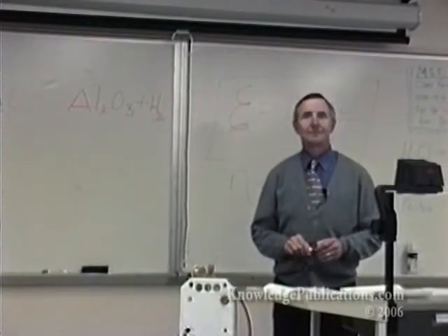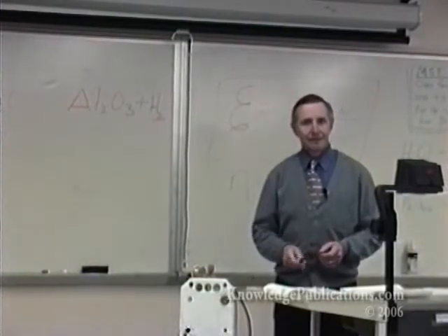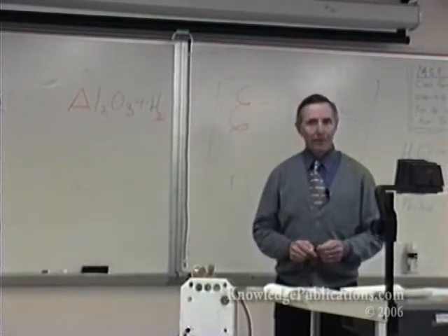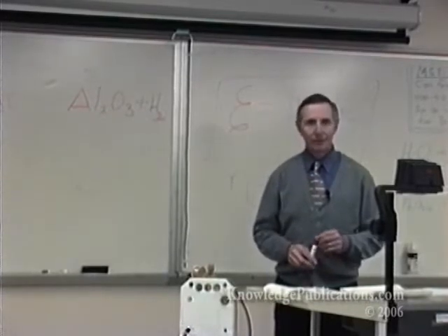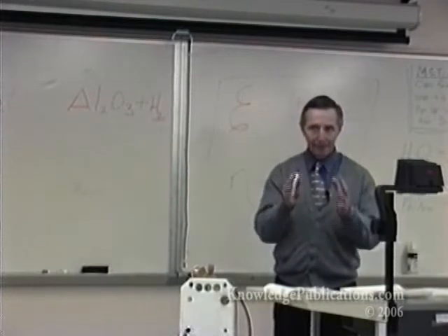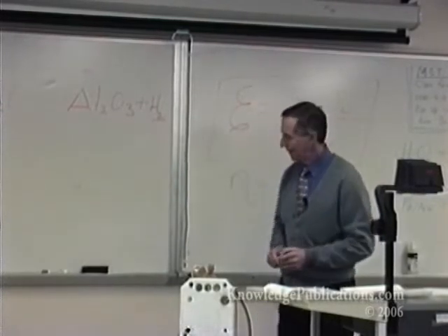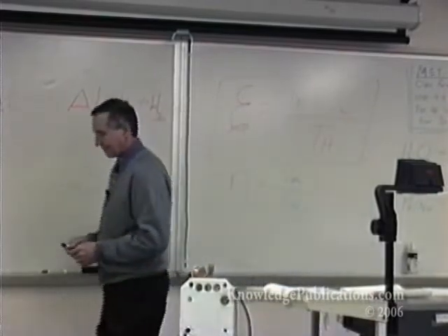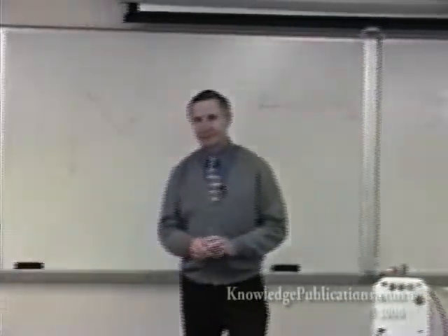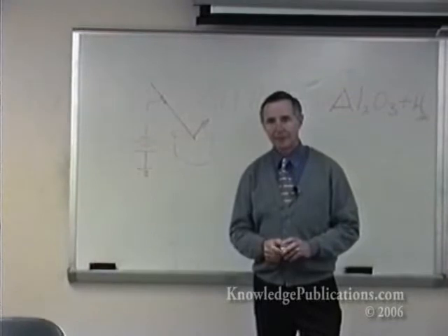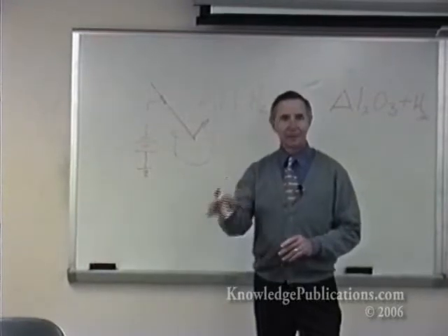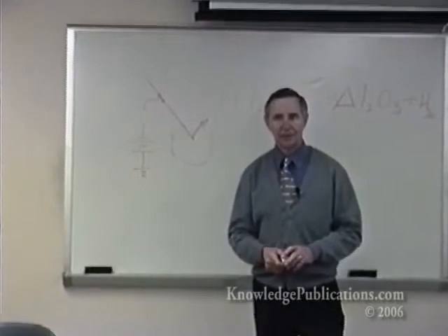That's right. Okay, so why isn't this pop can turning into hydrogen? It seems like aluminum and water don't want to react. That's why you have to interrupt the oxide on it that's protecting it. The oxide forms real quick on the surface of aluminum, and the electrolysis is taking it away. That's right. And this is room temperature water that we can start this with? You can run it at room temperature, and run it faster at higher temperatures.